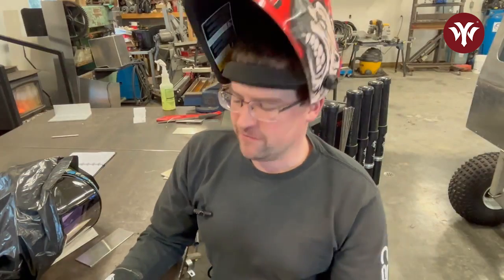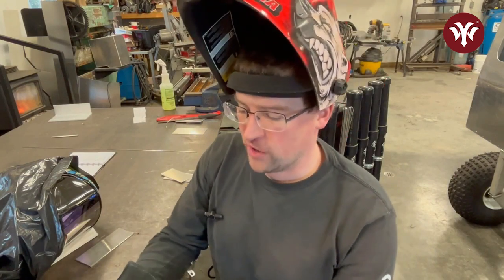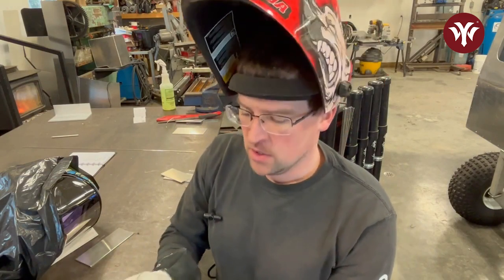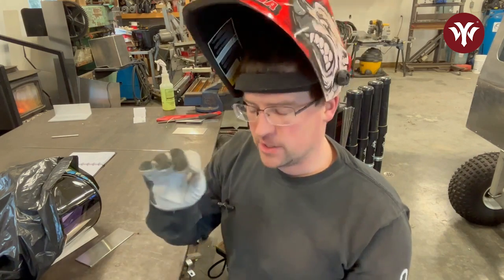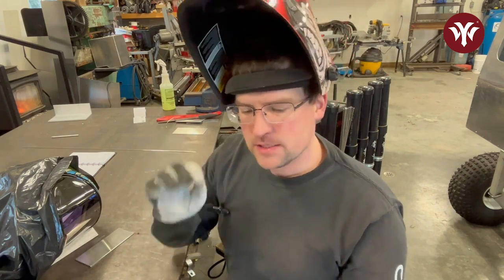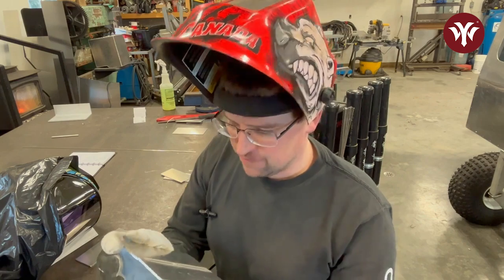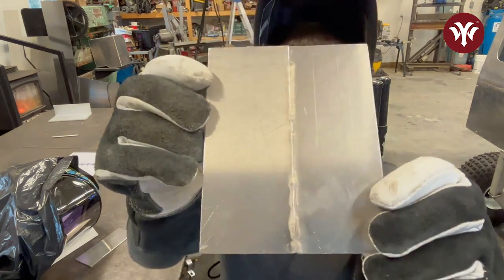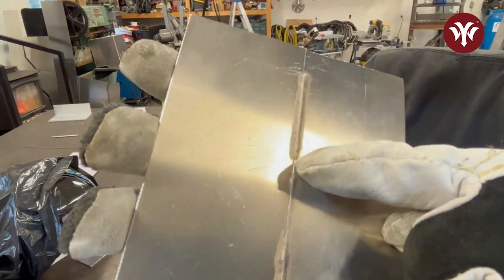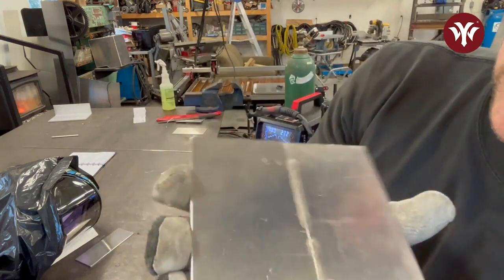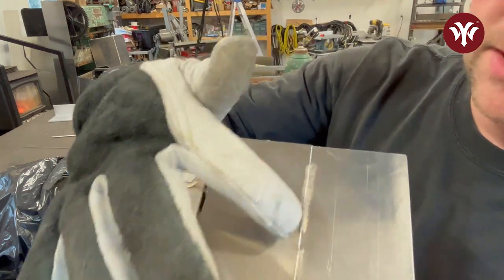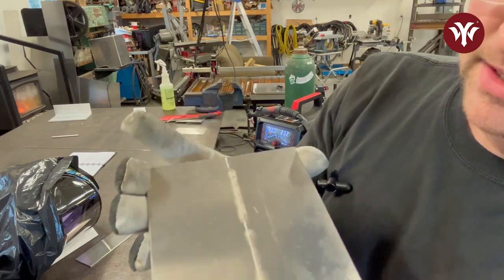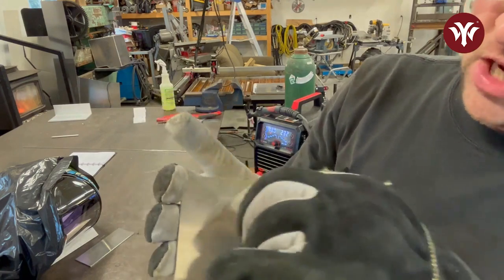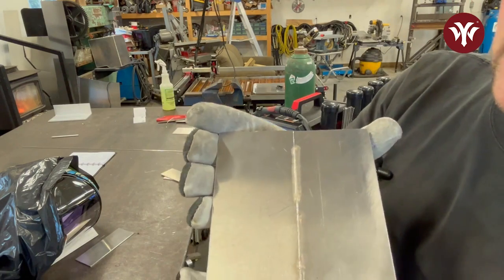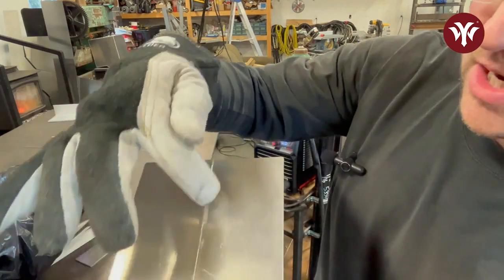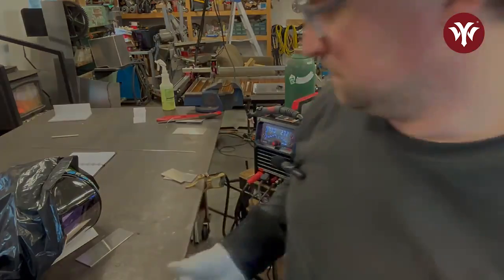The reason you want to crater fill is if you leave a crater there, that is a great spot for a crack to form. So you want to ramp down your current a little slowly with your foot pedal and dab just a little filler and fill that crater in. And as you can see here, we were getting wonderful penetration, and it looks like two separate pieces still, but that's only because the backside wasn't wire brushed, so that oxide layer is making it look like it doesn't really want to fuse together, but that is 100% penetration right there.